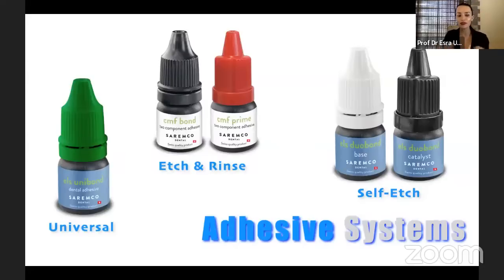And the main difference of universal and self-etch adhesives, you cannot use classical self-etch adhesives with acid etching on dentin, but you can use universal adhesives with acid etching on dentin, because acid etching of dentin with classical self-etch systems unfortunately decreases the bond strength of these adhesives to dentin.